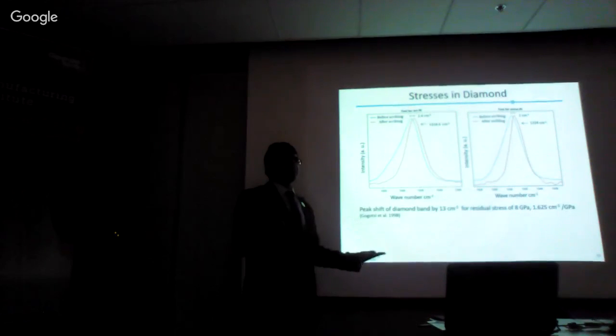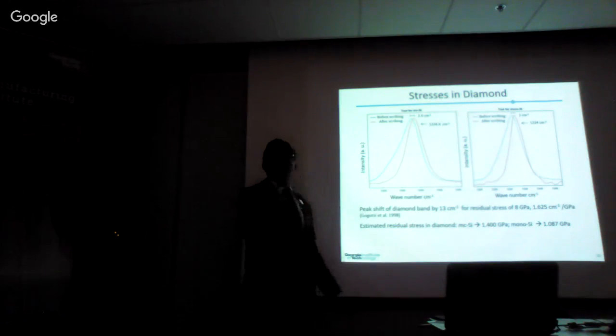If we look at prior literature about the peak shift of diamond for residual stress, we find that about 1.625 centimeter inverse of peak shift happens per GPa of residual stress. If we use that model and estimate the residual stresses created in these diamond abrasives, we find that the residual stress is about 1.4 GPa, compressive residual stress, for the tool scribing multi-crystalline silicon, compared to the tool scribing monocrystalline silicon having about 1 GPa.